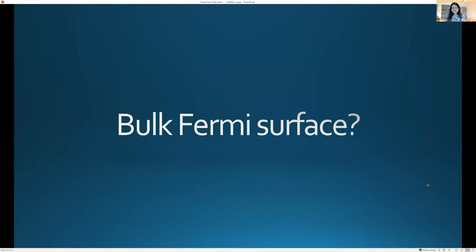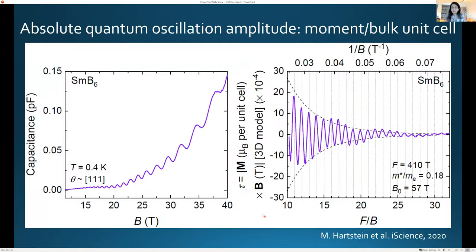And so we take the capacitance and convert this, using various spring constants of the cantilever, into Bohr magnetons per unit cell. And so we see that, okay, if the volume of the sample were contributing to this, how many Bohr magnetons per unit cell would these oscillations correspond to? And we get something on the order of 10 to the minus 3 Bohr magnetons per unit cell if this is coming from the entire volume of the sample.